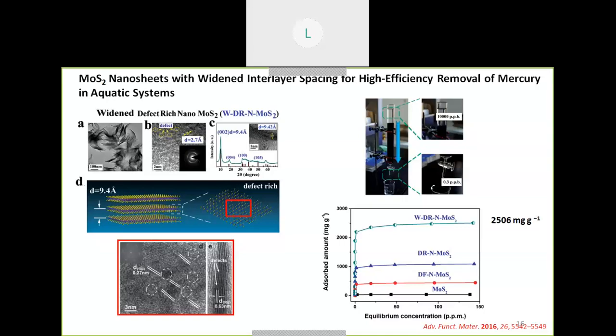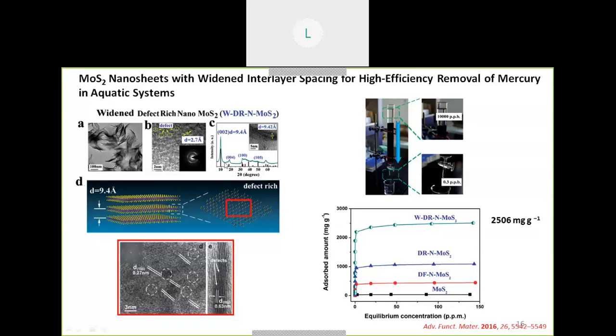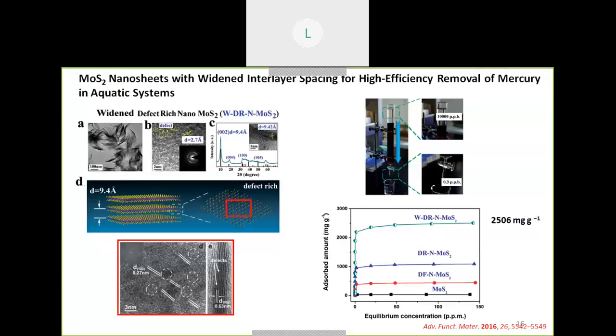They also verified it by XRD, with the shift. I haven't shown you the picture. The peak was at around 14 before, and the d-spacing was 0.63. Now the peak is shifted to around 10, and the basal plane, which is found to be 002, has a d-spacing of 0.9 nanometer or 9.4 angstroms. This increases the lamellar spacing and also creates defects where the binding capacity of the material was very high. They used this application for mercury removal, and you can see the difference in the adsorption amount, which was around 50 and has been raised to 2500. That is an excellent result shown by them.